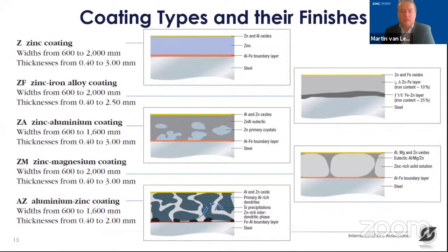The well-known coatings are the galvanized coatings, or the zinc coatings. These are applied in thinner or thicker coatings. The thin coatings are typically applied for automotive, whereas for construction products you typically go with the thicker ones. Then we have the galvannealed coatings, also called zinc iron alloy coatings, where the zinc coating is run through an annealing section after galvanizing to let the zinc react with the iron to get a zinc iron coating. The third category are the zinc aluminum coatings, which are typically used in construction. The fourth category are zinc magnesium coatings, which are used both in construction and in automotive.